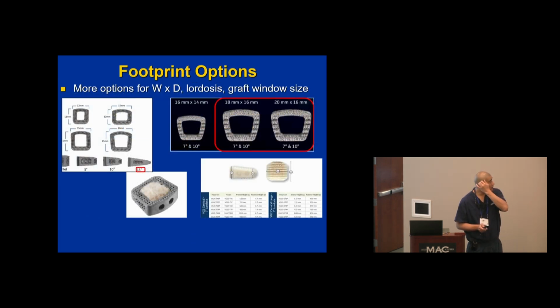This is probably the best part of metal. I think that trumps allograft, and it's the sizing. So whenever we used to use VG2, it really came maximum 12 or 14 deep. But as you guys know, the vertebral body can be long, particularly in bigger individuals. And VG2 only comes parallel or 7 degrees. So a lot of these cages now, they're 15-degree hyperlordotic, 15 by 15 implants, 17 wide. So if you go really wide, it used to be you put VG2 and you put it in, there's a whole bunch of space to the right and left of the graft, and you're like, this sure would be great to be able to graft this level. So I think the metal cages are particularly nice because of the footprint. And that, I think, is the main advantage of the footprint.